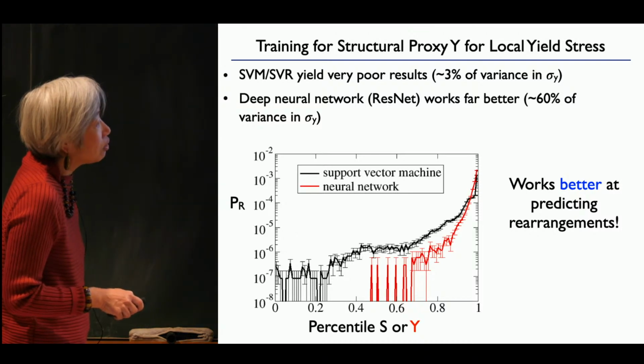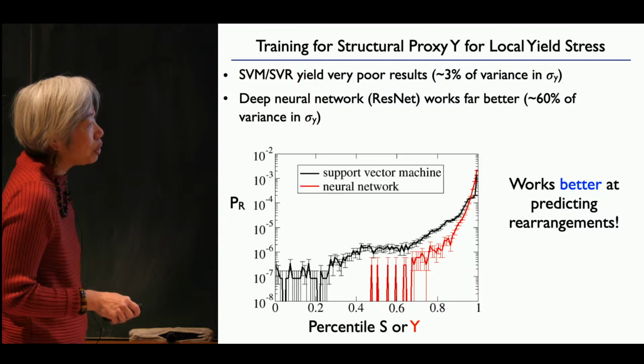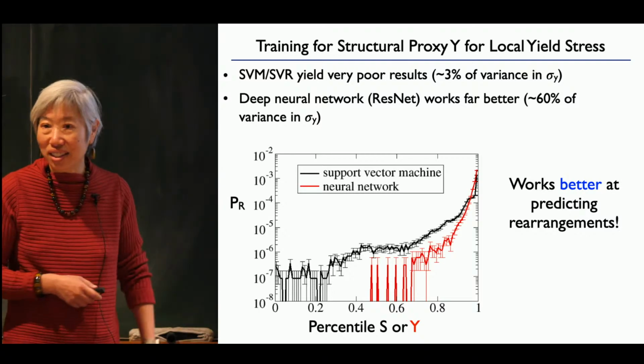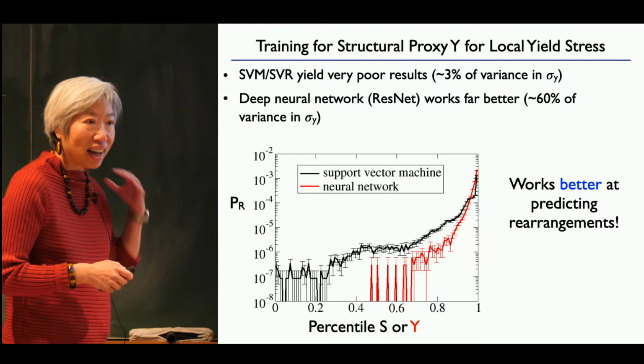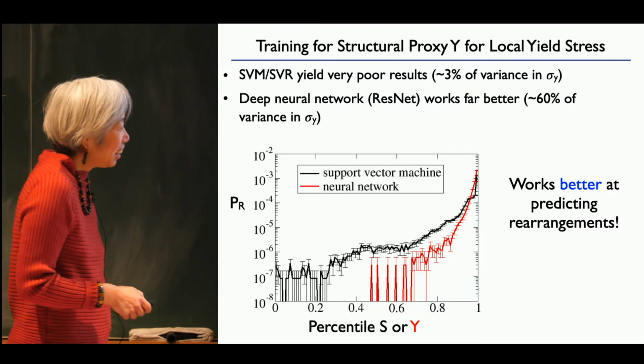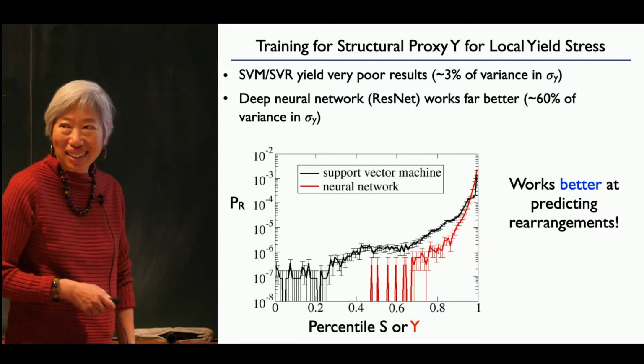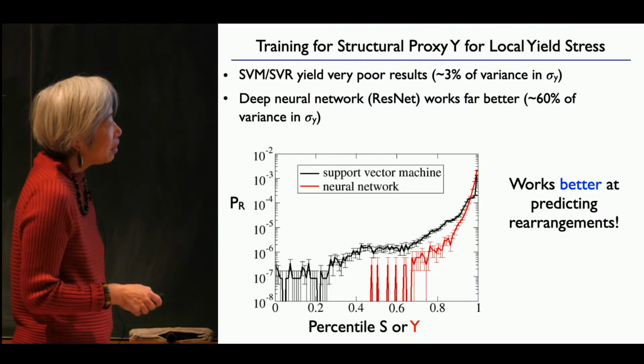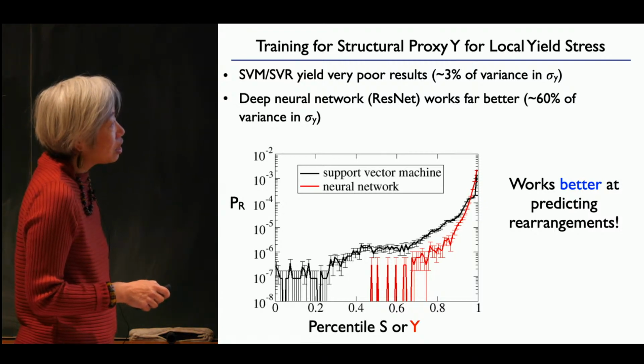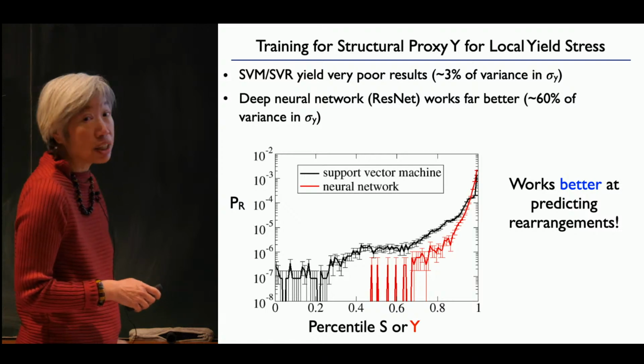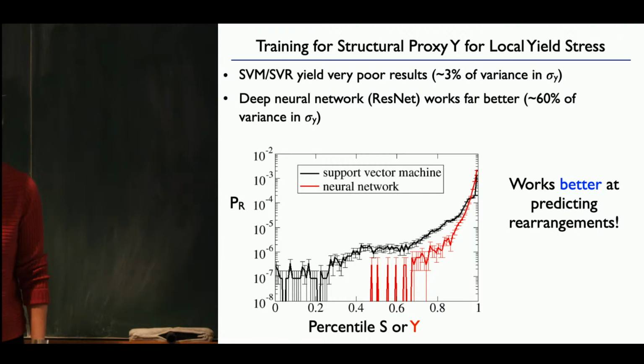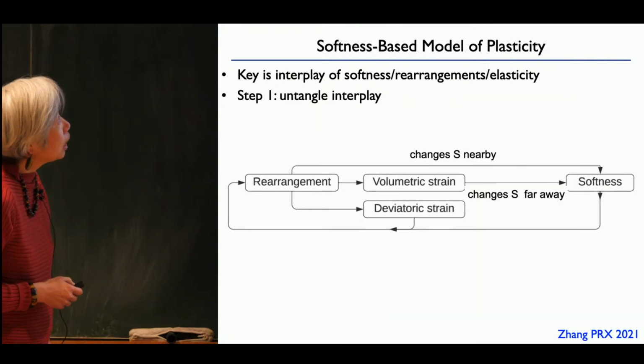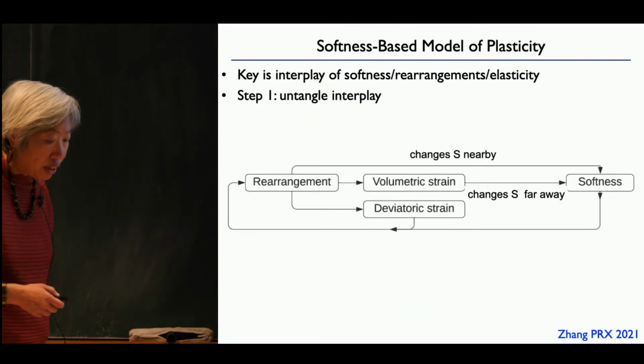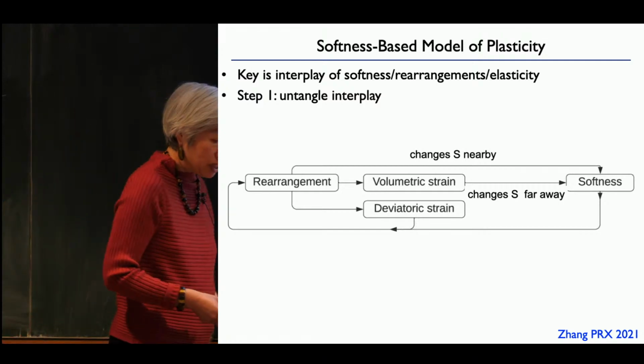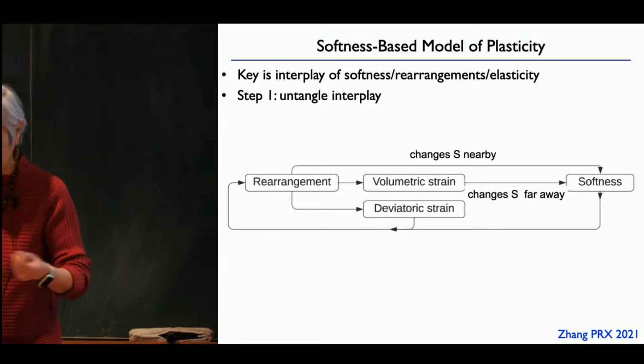So what you see is that over the percentile range of the structural predictor of yield stress, which I will not commit the crime of calling yieldness, we just call it Y. Okay, so this is our structural predictor. Over this rather small percentile range of it, you see the probability of rearranging changing by many orders of magnitude. So it's quite sensitive. All right, so now we have this quantity. What do we do with it? What comes out of ResNet is a quantity that's between 0 and 1.